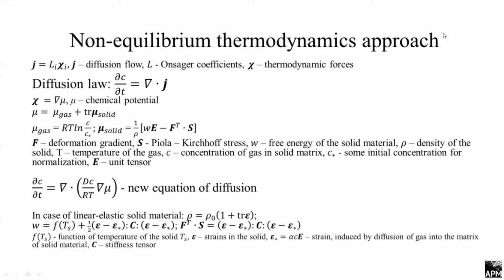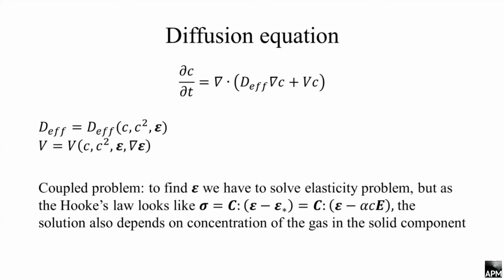Then we obtain a new equation of diffusion. Not to overload with matrices and equations, let's go to the diffusion equation. I just want to note that when we write the stress-strain state, we neglect all the plastic stresses and strains appearing in the metal, because first we want to verify our model and see if it works and describes this boundary layer formation. So we use a linear elastic model of the metal. We also say that there is an induced strain which appears because of the diffusion of hydrogen in the metal. So basically we obtain a new diffusion equation where the diffusion coefficient depends on concentration, strains and also gradients of strains.